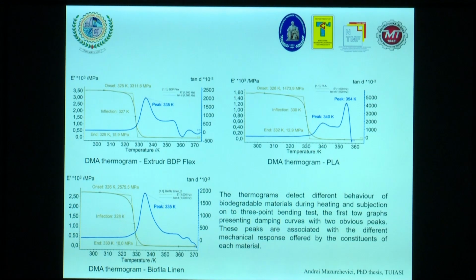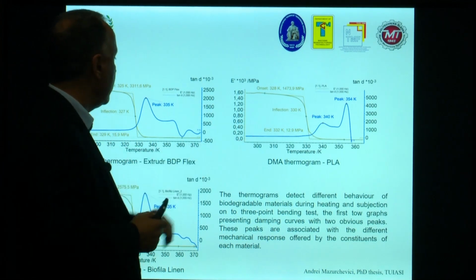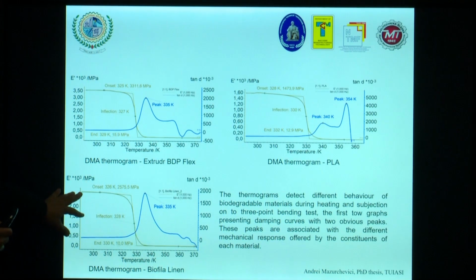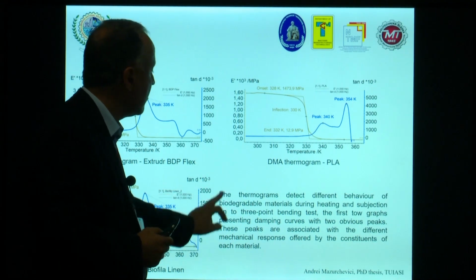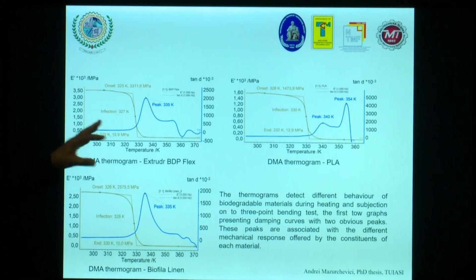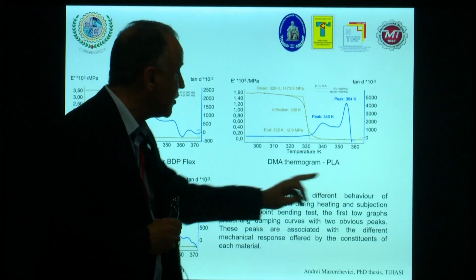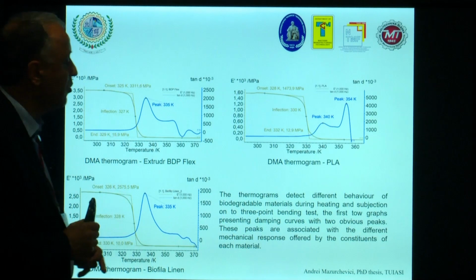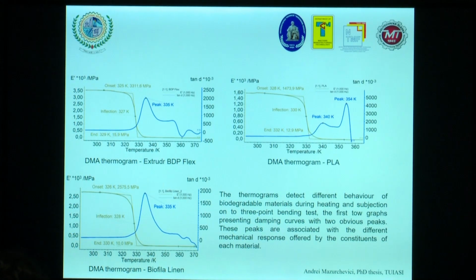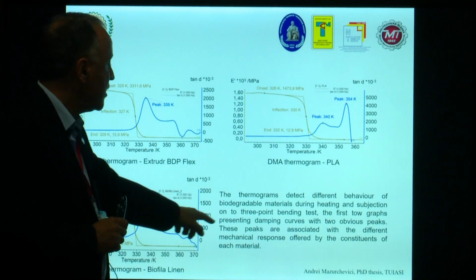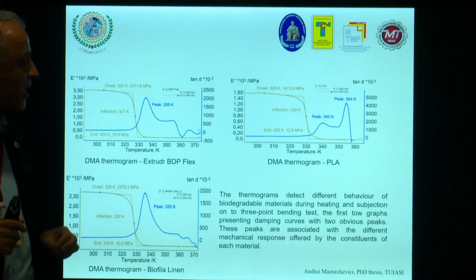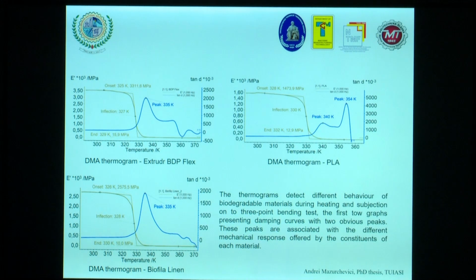DMA thermogram in case of BDP Flex, DMA thermogram in case of PLA, and in case of Biofila linen. I put some conclusions: the thermograms detect different behavior of biodegradable material during the heating and subjection to the 3-point bending test. The first two graphs present damping curves with two obvious peaks, 1 and 2, and these peaks are associated, as I mentioned, to the different mechanical response offered by the constituents of each material.